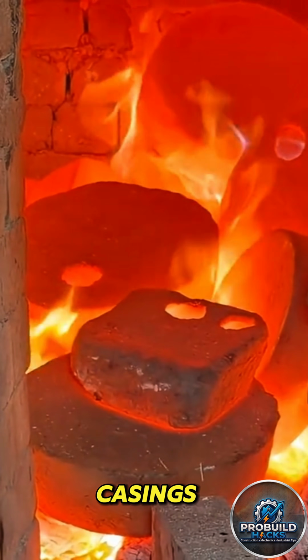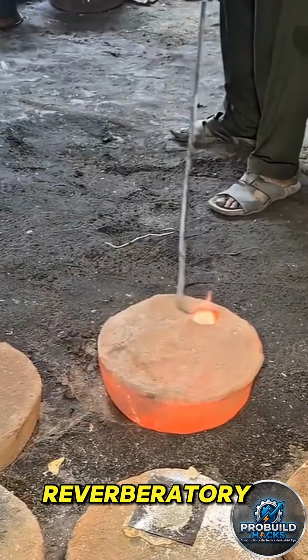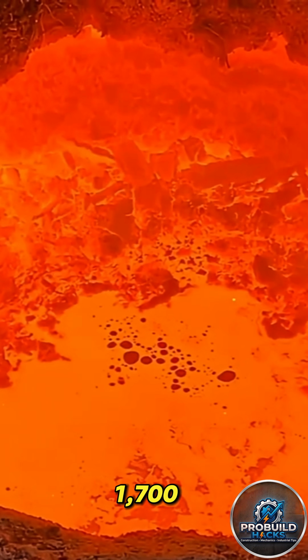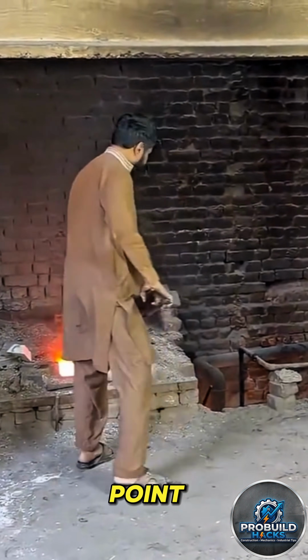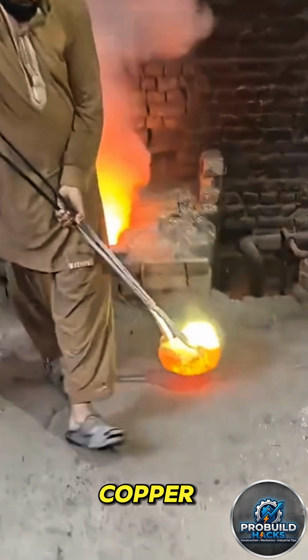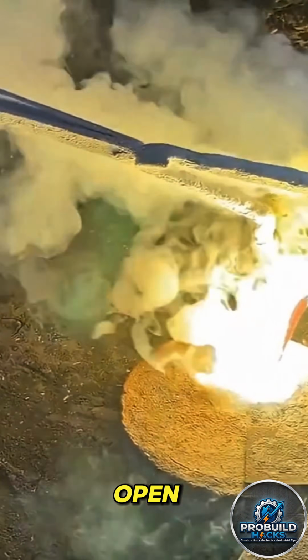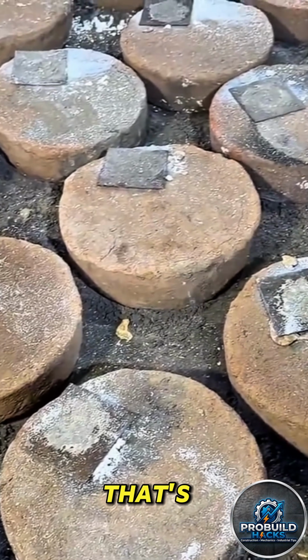The brass casings are fed directly into an open fire reverberatory furnace. Temperatures hit over 1700 degrees Fahrenheit, past the melting point of brass. The zinc burns off first, leaving a copper-rich melt. That open flame you're seeing, that's the zinc vapor igniting.